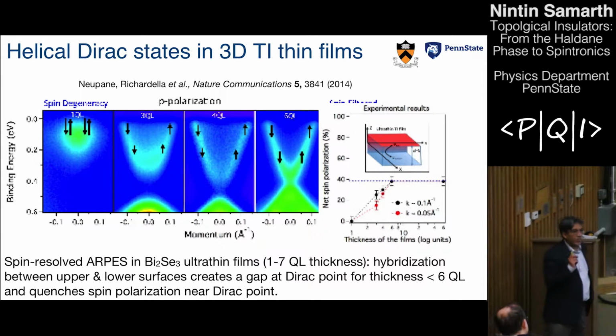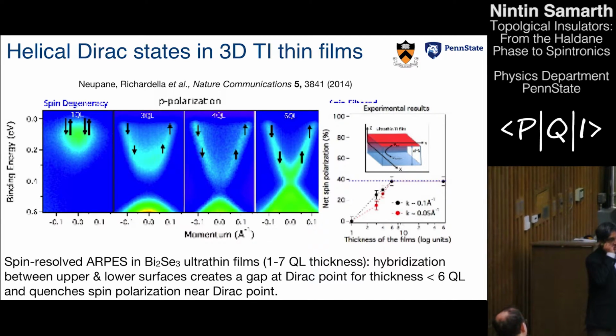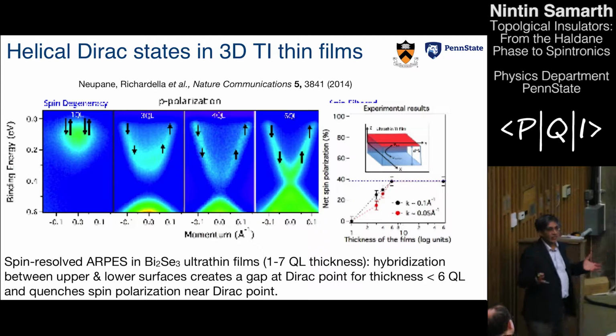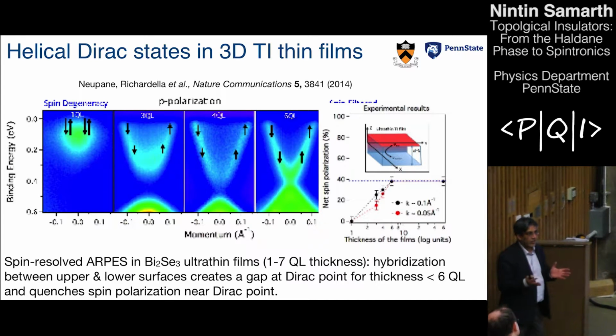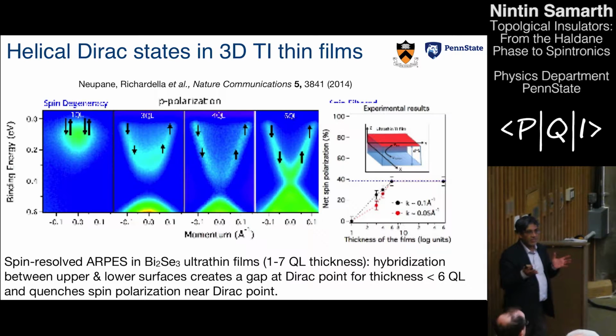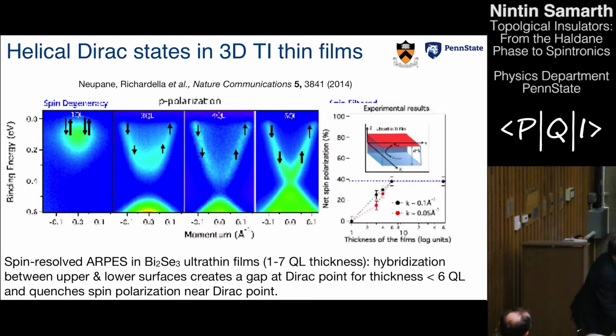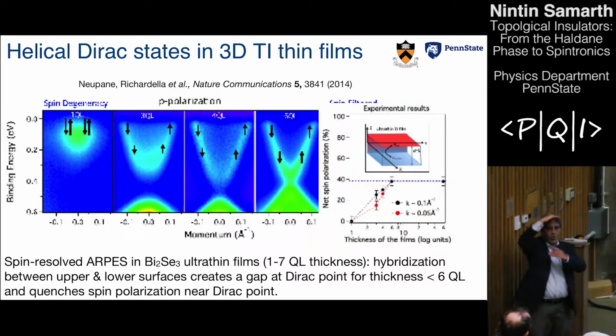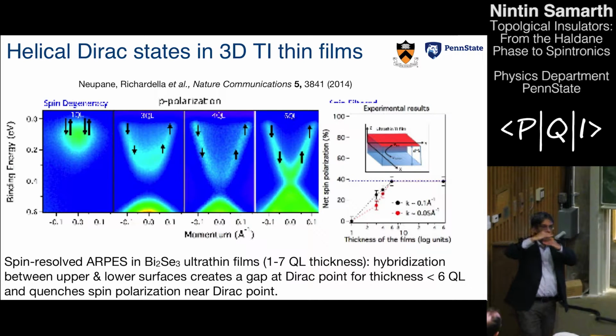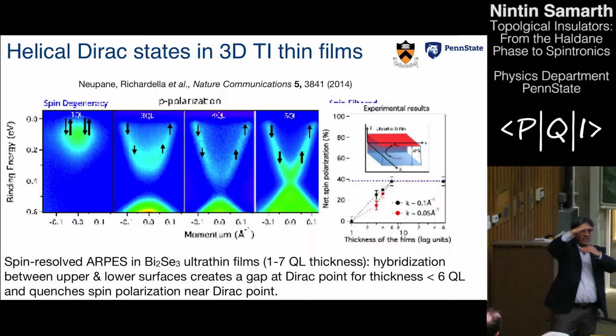So once you start growing materials of this kind, you can essentially do band structure physics. So you can map out how the wave functions and how the energy states behave as a function of quantum confinement. So for example, imagine that you take a crystal that is extremely thick, right? On all the surfaces of the crystal, I have these Dirac states. But as I start making the crystal thinner and thinner and thinner, at some point, the wave function of the Dirac states on the top and bottom surfaces will start coupling to each other.